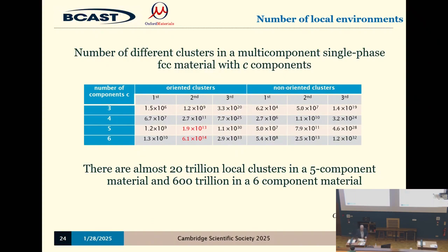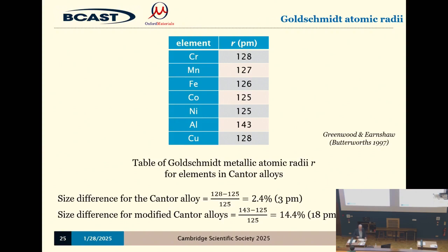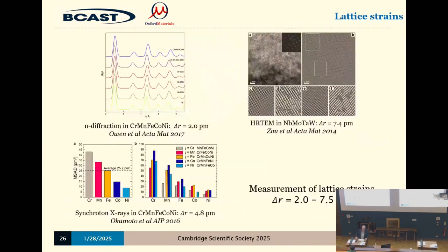And is it true that they have a lot of strain? Well, if we take the 5 components here in the Cantor alloy, forget these 2, the size difference is about 2.5%, which is about 3 picometers. And 2.5% you would expect, therefore, is a big strain. That's what it would be if they didn't change their size when you mix them. But we've also got measurements of what it is, and it turns out that's about right.